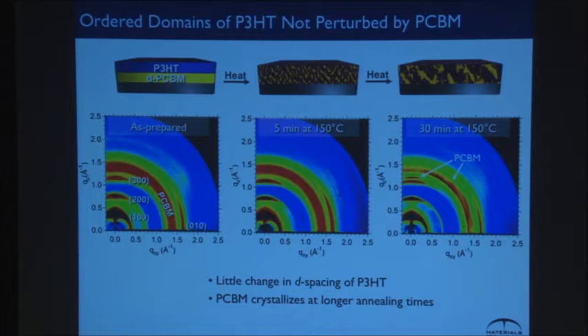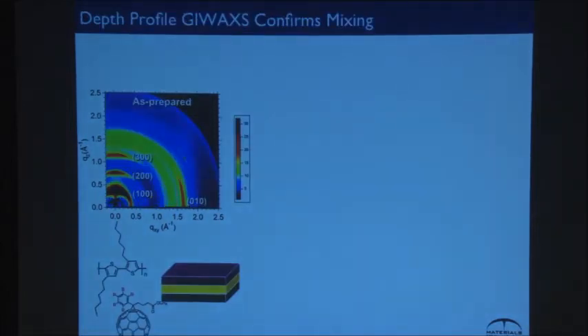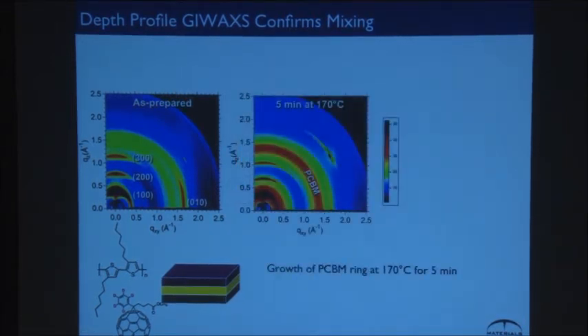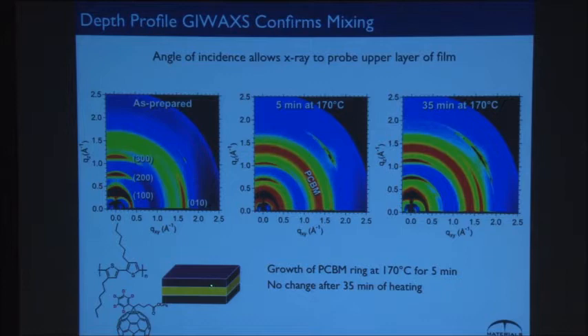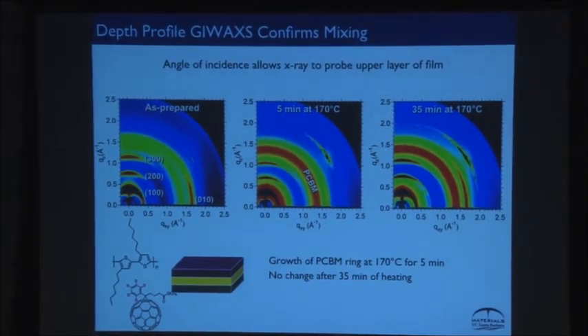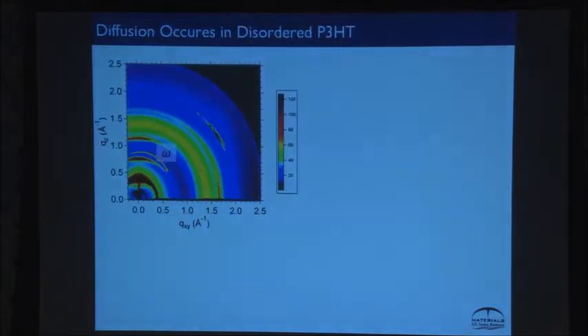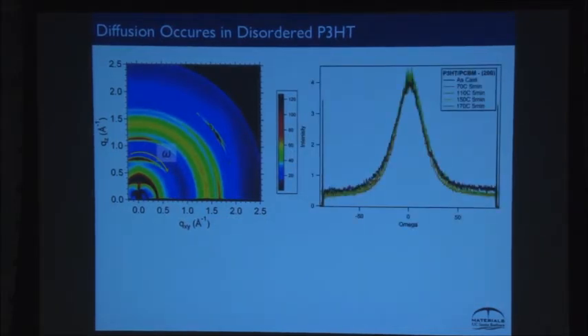Okay. Now, when we look at this, we can confirm this in other ways. We can actually do depth profiling. We can sit at the top and heat the film and watch the fullerene diffuse in, where we're doing kind of surface-oriented scattering. So we do this a lot of different ways. We've done this where we flip this. It's not an effect of having the fullerene on the bottom or the top. Doesn't matter. Okay. Now, what's funny about this is when I look at the diffraction, what you find is if we look at the rocking curves, this is the orientation of the crystallites.